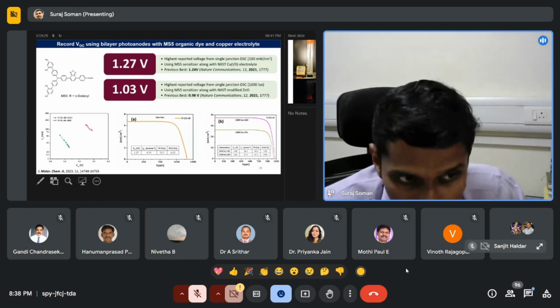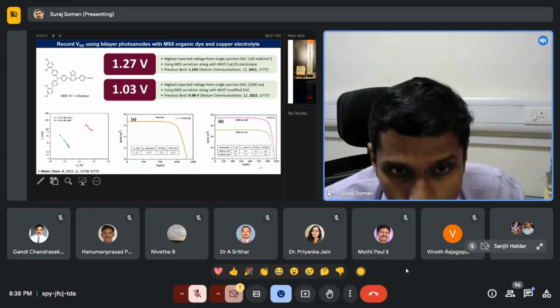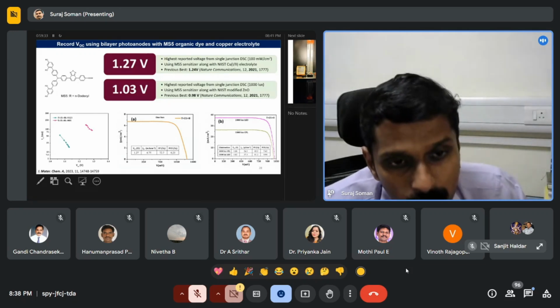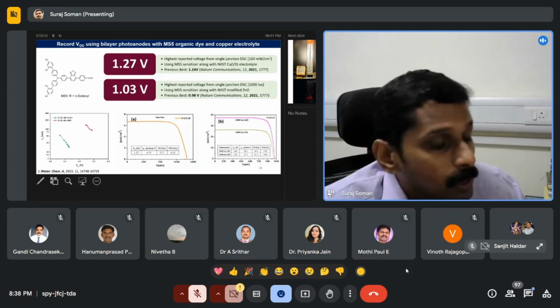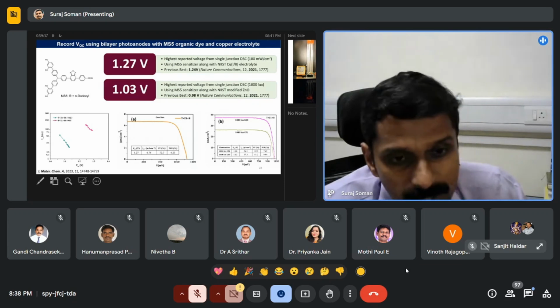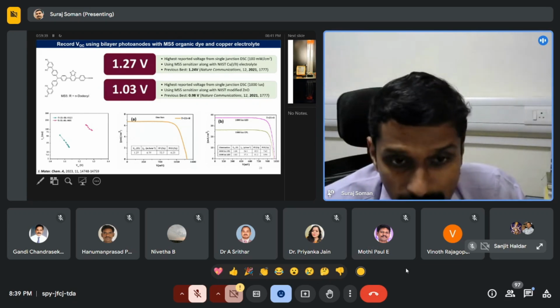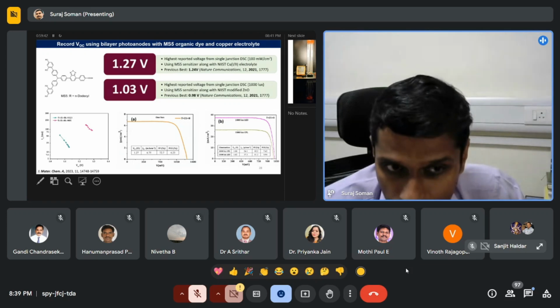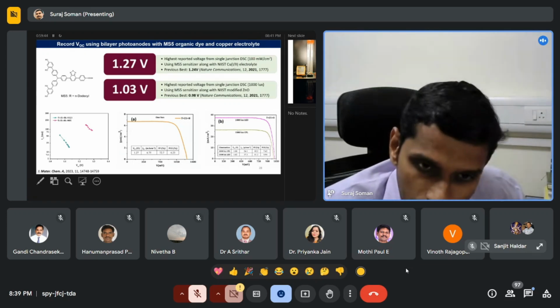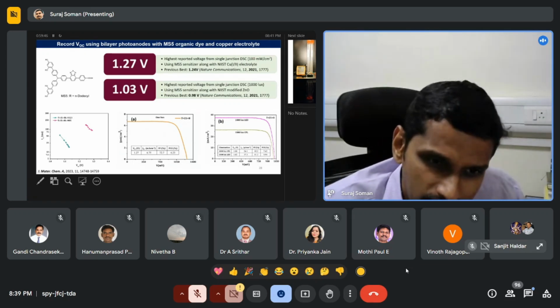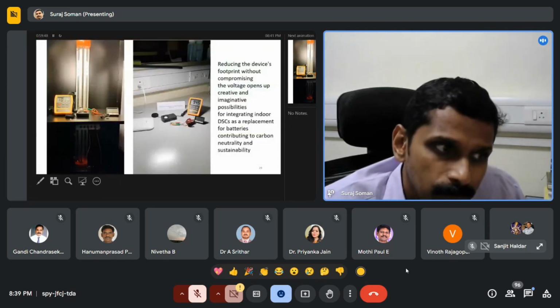And this is under the one sun condition, and under the indoor light you can see that we are able to realize voltage of around 1 volt. So what is the importance of this voltage? And here you can see the efficiencies are not high. It is not 30% or 40%. It is only less than 10%. But that efficiency is enough in a way to power certain gadgets.